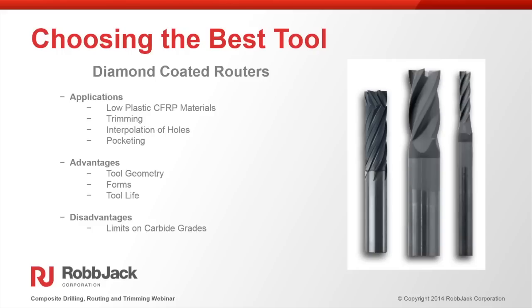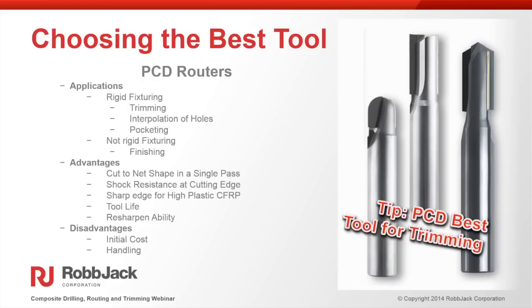Typically, the diamond coating works better in the lower plastic content composites. When you get into the higher plastic content, the sharper edge of the PCD tends to work a little bit better. The other thing to remember with anything diamond coated is the limits on the carbide grade. When you diamond coat, as we talked about earlier, you leach out the cobalt right on the surface where we're going to coat and then grow the diamond. If you don't leach out that cobalt, you'll form a graphite layer before you grow the diamond, so the diamond coating will just wipe right off. So you can't take every carbide tool and get it diamond coated. It typically has to be a specific carbide grade that's compatible for diamond coating.